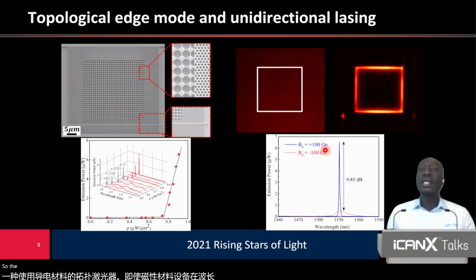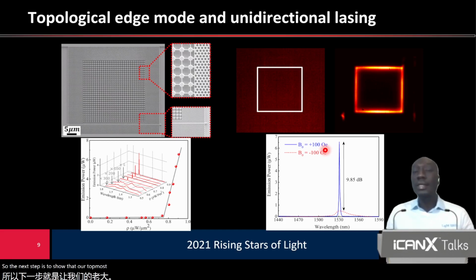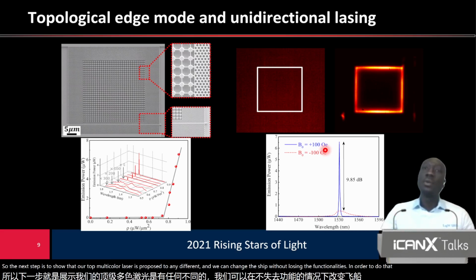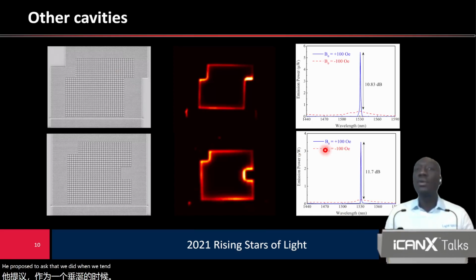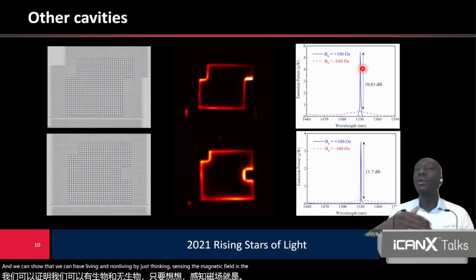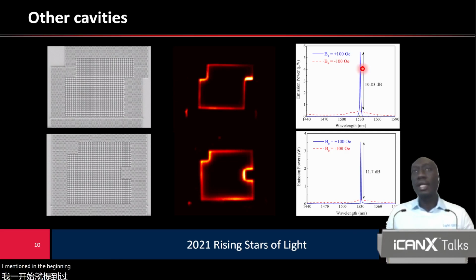The next step is to show that our topological laser is robust to defects, and that we can change the shape without losing the functionality. In order to do that, we propose two other cavities where we change the shape of our photonic crystal cavities. You can see here we have the edge state very well defined, and we can show that we can have lasing and no lasing by just changing the magnetic field, with an isolation of almost 11 dB.